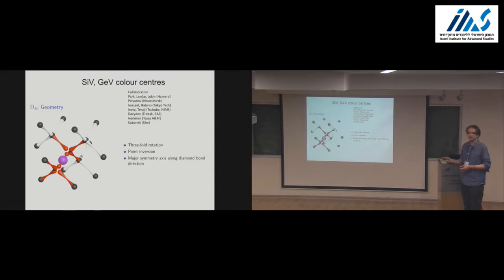It has an inversion symmetry, and it has a consequence on its spectrum. Because the atom does not possess any permanent electric dipole moments, the Stark shift for this system is only a second order effect. So small fluctuations or small variations of the electric fields at the location of individual atoms in a solid state will not lead to any spectral shifts, and we expect that these atoms will be much more spectrally homogeneous.